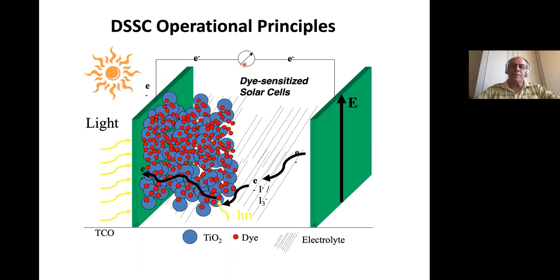We go to the plus and we reduce the electrolyte, and then the electron is brought back to the dye, and we can start working again in the next cycle, so to speak. So the processes here, we call electron from the dye to TiO2 injection, and bringing the electron from the electrolyte to the oxidized dye, we call the regeneration.